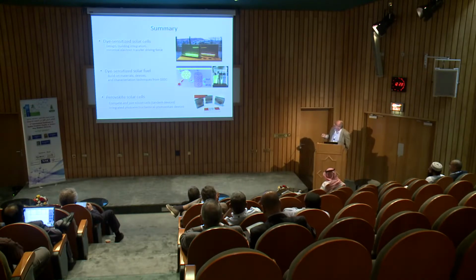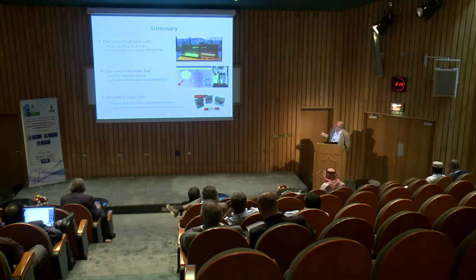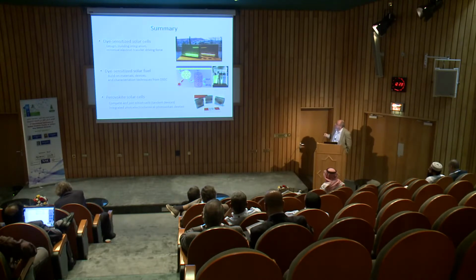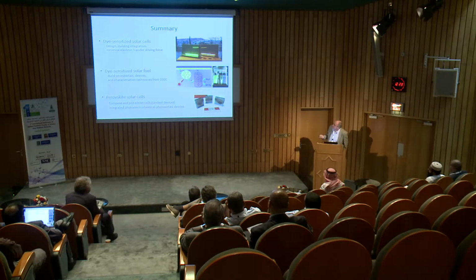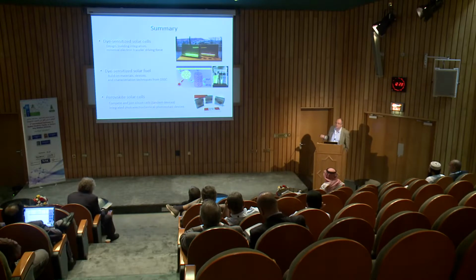We think we have a very nice possibility with copper redox systems at the moment. There is an emerging field I didn't talk about, which concerns not making electricity, but making hydrogen and oxygen with this kind of molecular catalyst and molecular light absorbers. It's a growing research field. For the perovskite solar cells, it's a big discussion if we should think about competing with silicon or perhaps rather join silicon cells in tandem cells. And they can also be used, because of high voltage, to drive water splitting systems.